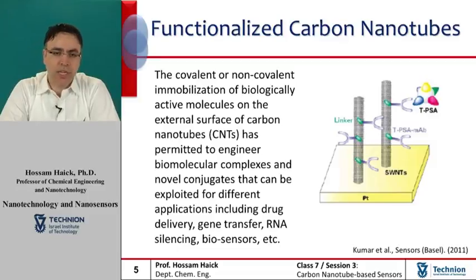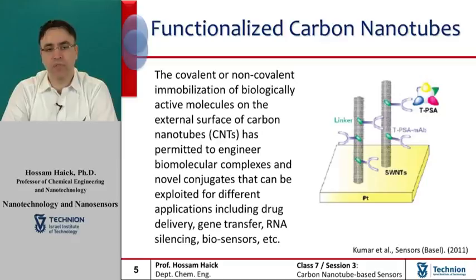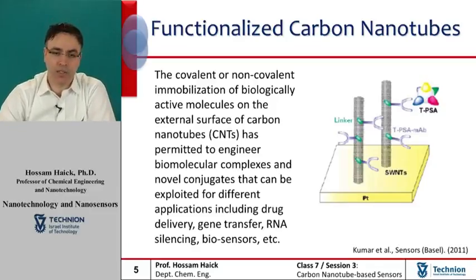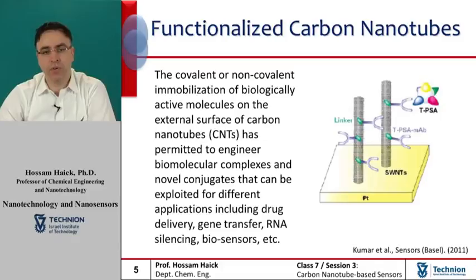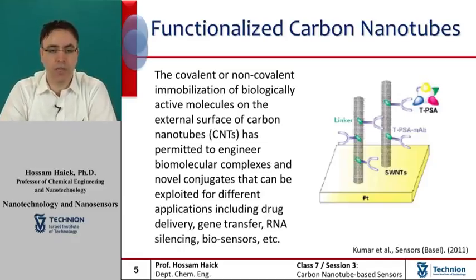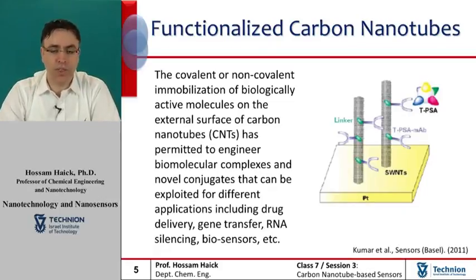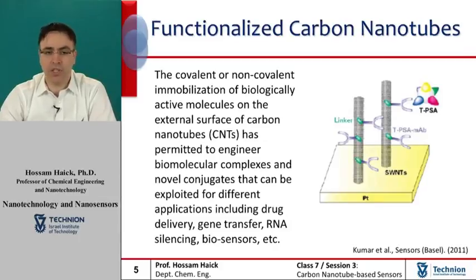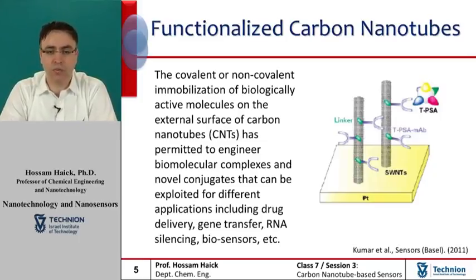In the presented image, you can see an electrochemical microelectrode containing platinum along with modified single-walled carbon nanotubes, which is mainly used for label-free detection of analytes. Electrochemical signals at various concentrations are recorded using differential pulse voltammograms. An increase in the current is noticed due to the increase in concentration of the PSA. It is confirmed that the addition of PSA onto the antibody attached to the single-walled carbon nanotubes leads to an increase in current. A slight defect in the monolayer due to compact packaging of the antibody on the carbon nanotube surface could cause a high electron transfer rate along the electrolyte and the carbon nanotube.